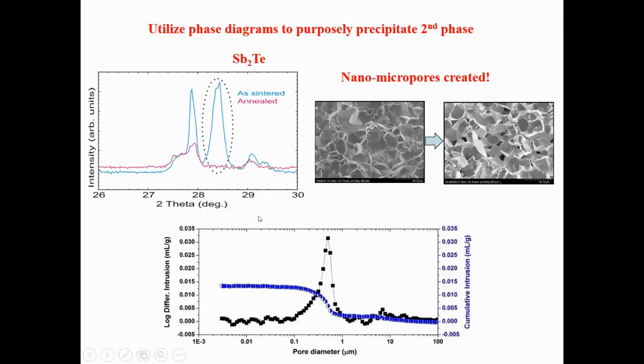So of course the time is limited, so I go a little quick. But basically we had a very simple way to create a nanostructure: just precipitate this secondary phase, with low melting point, and just anneal. You only have to anneal it and it creates these pores. So these are micropores, probably these ones here, but the majority of the pores are nanopores.